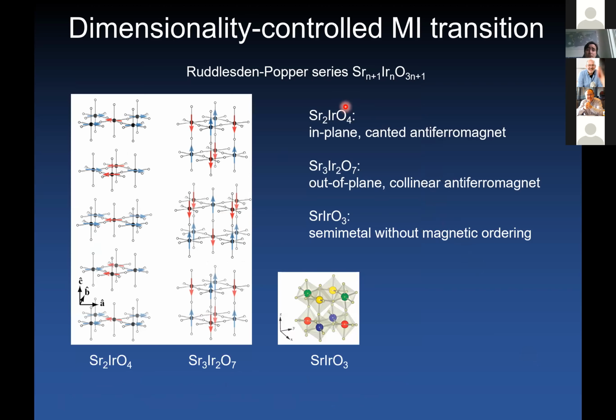And if you already look in the bulk, we see that these materials can go through a dimensionality controlled metal to insulator transition. So in the two-dimensional limit, where you realize the Sr2IrO4 phase, you have a fairly decoupled two-dimensional iridium oxide plane with a narrow band, and these systems undergo a Mott instability, and so they show a correlated Mott insulating ground state that is also antiferromagnetic with an in-plane magnetic moment and a strong canting of the spins, which is caused by this unusual J effective 1/2 physics. So it's remarkable that the spin canting is exactly equal to the octahedral rotation angle.